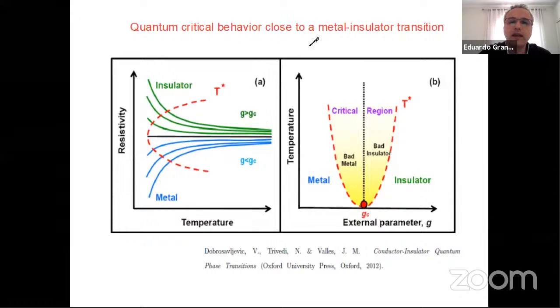So I want to mention that in this work we are looking at quantum critical behavior. What's a quantum critical transition, and how does it apply to this kind of system? I mentioned before that the system is insulating because of the gap opening caused by the spin-orbit and the correlation effects. So we are interested in inducing a metal-insulator transition in this system, first to perhaps induce superconductivity, and second, perhaps to look for new physics that may arise when the lower and upper Hubbard bands touch each other. So from a basic physics point of view, not much is known about what should happen.